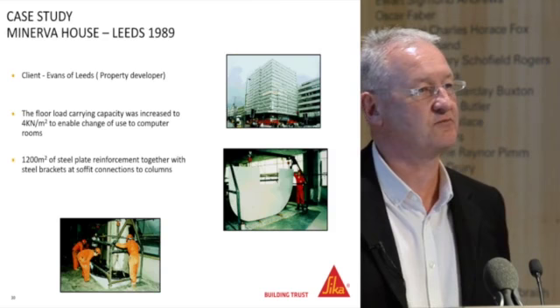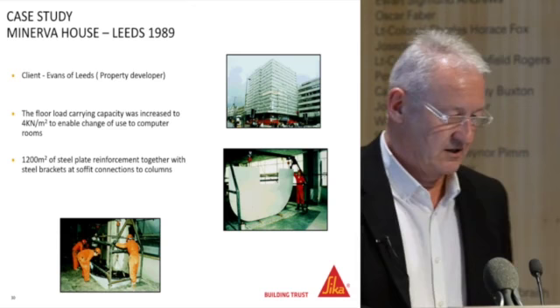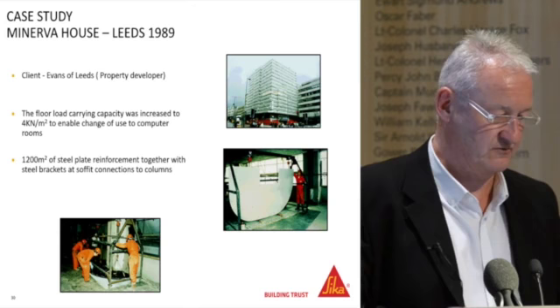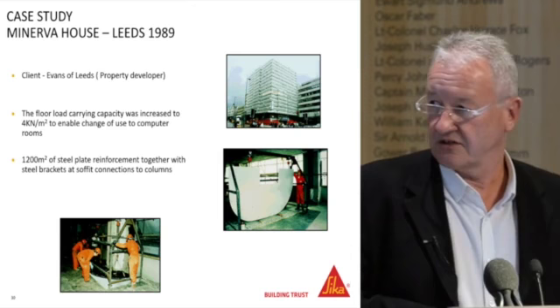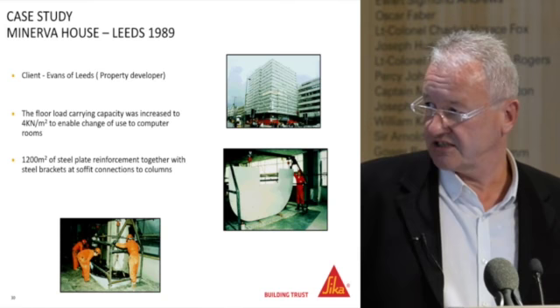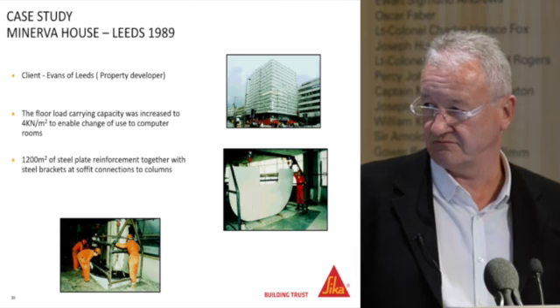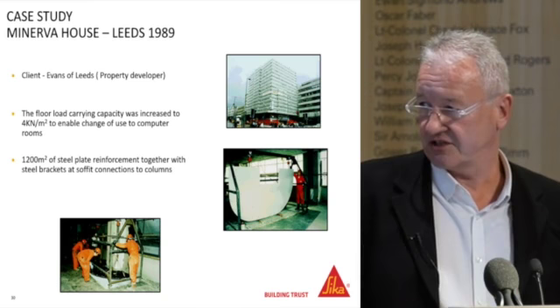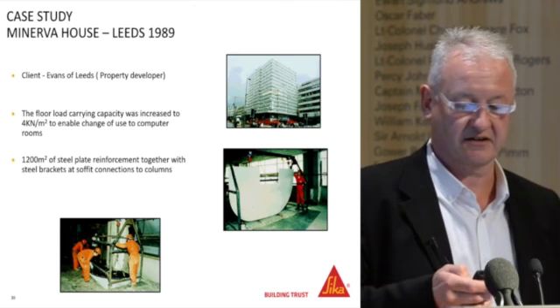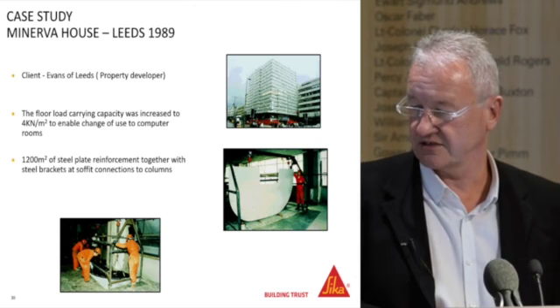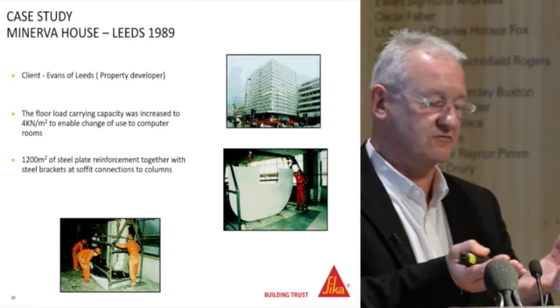A couple of case studies to finish. Minerva House, Leeds — done in 1989 for a property developer upgrading the building's floor loading, increased to 4 kN/m². 1,200 square metres of plate were used on the soffit of the concrete. You can see here they used a special A-frame so they could hang the plate off it — fabricated with corrosion protection applied, degreased in situ, adhesive applied to the concrete, the two surfaces brought together, with a little kentledge on top to apply pressure and extrude adhesive from the sides. You can also see half-moon plates placed on the external columns, with two plates on the internal columns to completely encapsulate the base.